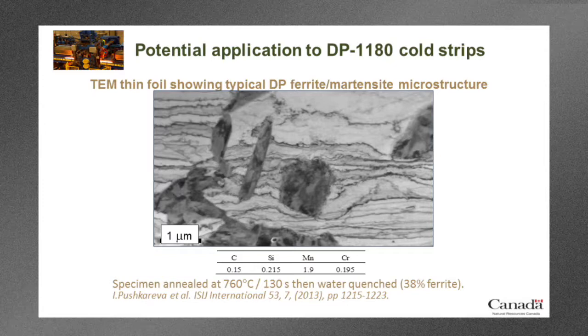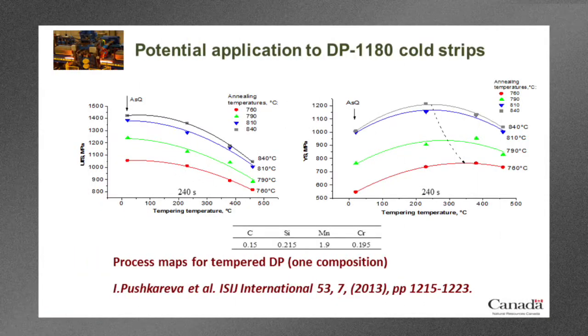So this particular steel, the chemistry is given below. It was 0.15 carbon, 0.2 silicon, 1.9 manganese, and 0.2 chrome steel. And this was annealed at 760 degrees C, so it's about the same annealing temperature as we used for the trip steel in the previous example. Held for 130 seconds and then water quenched. And this one had 38% of ferrite in the final microstructure. And the reference for that you can find below. On this slide, I'd like to show you some of the mechanical properties of this steel from the previous slide. So here are two graphs.